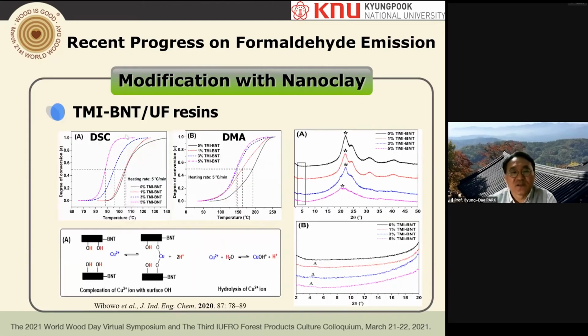And then we add the TMI bentonite. That means the transition metal ion modified bentonite, which is modified nanoclay, mixed with the UF resins. Actually, it's cooked in the kettle. When you have 5% of the modified nanoclay, you have much faster curing detected by DSC. The same thing is detected by DMA: much faster than the control. What was happening here? We explained that the copper ions are hydrolyzed and release protons, which accelerate the cure of the UF resin. That's why the modified resin has faster curing.